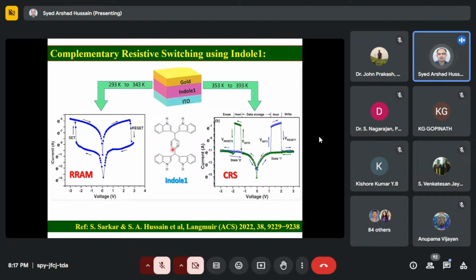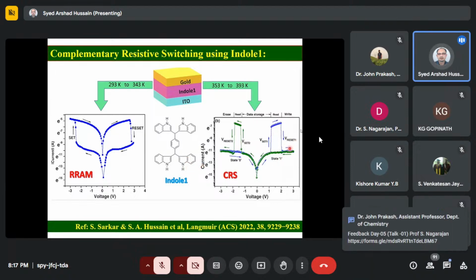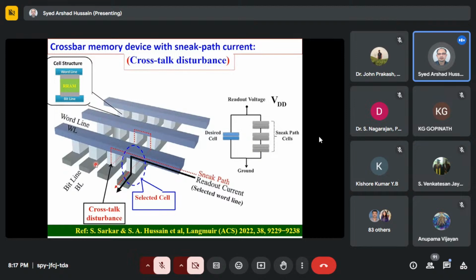Then we have seen that this molecule showed bipolar switching, just the earlier example. Here we increased the temperature and exposed the molecule to very high temperature, and we have seen that within this temperature range, the nature of switching changes from bipolar to complementary resistive switching. Okay, this is very important, complementary switching, because with bipolar switching, in the zero state your device is at high resistance state, but when it is in the on state, your device is at low resistance state. There is conduction between the two electrodes.